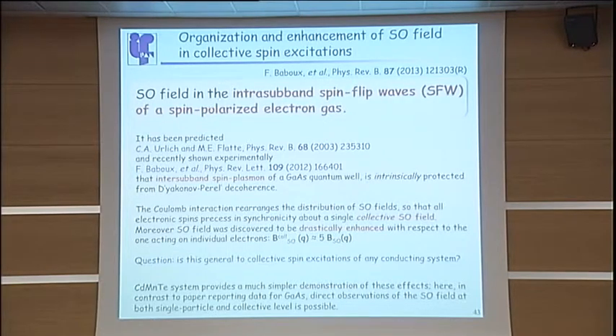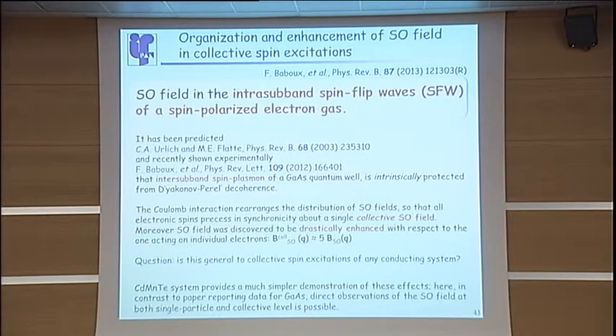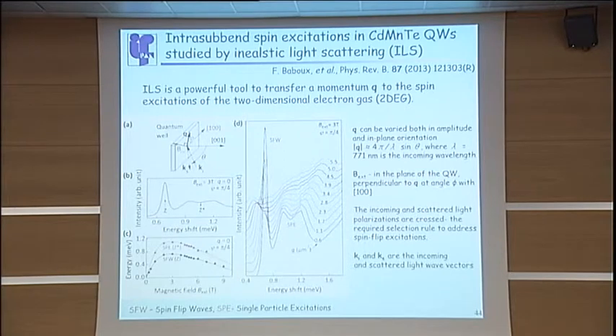Now, since I don't have too much time, I only want to tell you that our structures were used by our French colleagues to show the spin-orbit field for intra-subband spin wave excitations, and what was predicted some time ago and recently shown in the case of inter-subband spin plasmons, that those excitations are intrinsically protected from Dyakonov-Perel decoherence. However, and also, the spin-orbit field acting on this collective spin excitation is drastically enhanced. And so our system happens to be convenient because in our system it was possible to observe in the same sample experimentally both the spin-orbit field at single-particle and collective excitation level.